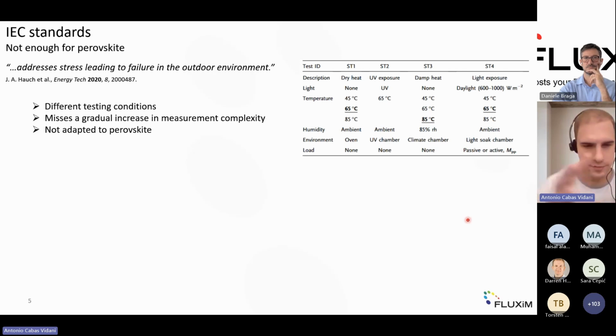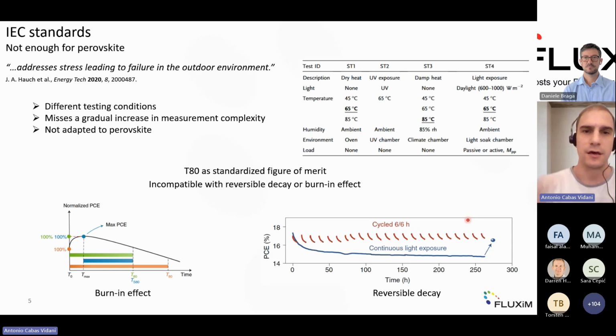So they try to replicate a specific set of conditions that you find outdoors, but one thing they miss is a gradual increase in measurement complexity. This means that if you take a protocol, you need a very specific set of facilities, equipment and tools to recreate the protocol instead of starting from a simpler level. And then they're not adapted to perovskite. For instance, if we take the T80 as standardized figure of merit to assess the stability of perovskite, this figure of merit is difficult to make compatible with special decay behaviors typical of perovskite, like the burn-in effect that you see here on the left, where the performance first increases and then decreases, or the reversible decay, where if you cycle, so you turn the light on and off, the loss in performance is recovered after a time in the darkness.